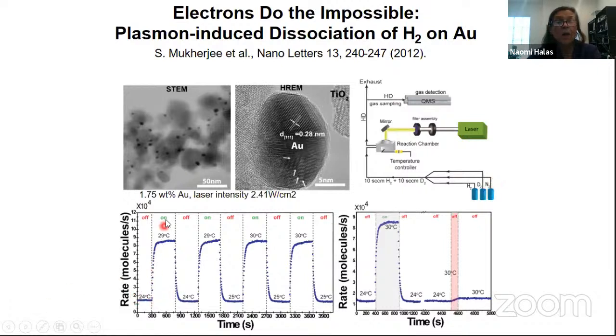When the light is on, we see there's a little temperature increase, but that's not nearly enough to actually dissociate H2. So it's not a thermal process. It's just a few degrees. Then we turn the light off, it goes back down, and when the light is on, we see this clearly. It's a light-induced process. It's not a thermal effect. It is a purely hot electron effect.